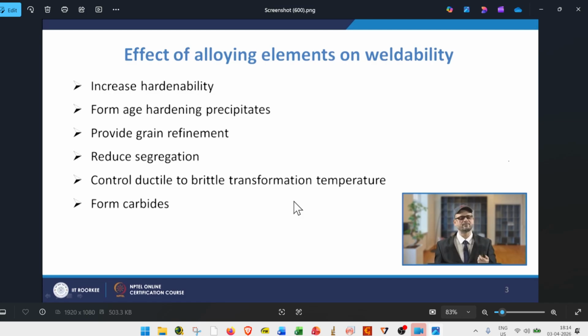And next, formation of carbides. In the case of stainless steel and so on, the chromium may tend to react with carbon from the matrix and form chromium carbide. So such kinds of carbides may also form. These are all the effects of the alloying elements.